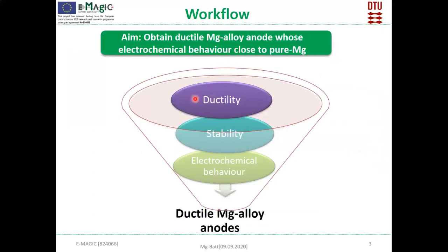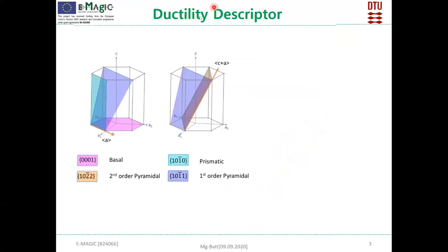In the first step, we were screening the dopants. First we looked at whether the dopants we added improve the ductility. For that we started with 33 dopants which are already known to improve the ductility from previous studies. Then we checked whether these alloys are stable. After that, we checked the electrochemical behavior of the magnesium alloy, which should be closer to that of pure magnesium. And for that, the first thing we have to study is the ductility.